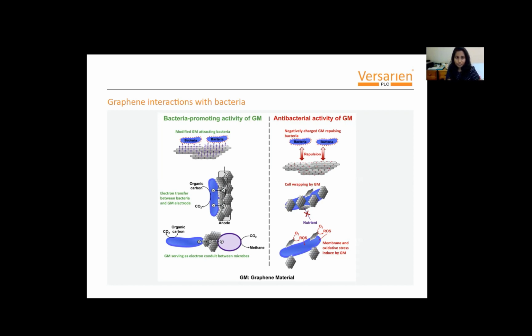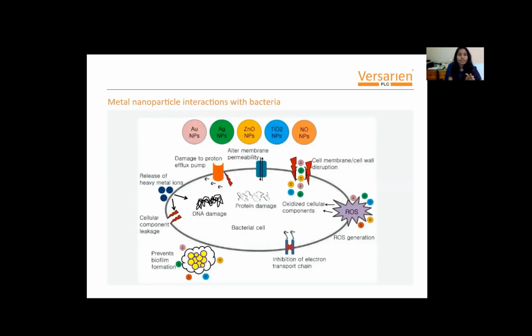Surprisingly and interestingly, graphene materials can promote bacterial activity as well. This all depends on the physical, chemical, electrical, and structural properties of the graphene material that you use. For example, if the surface of the graphene material is positively charged, the negatively charged bacteria are attracted to the surface and get adhered. Then the graphene material can act as an electron donor or electron acceptor and promote the metabolic pathways of bacteria. This is going to promote biofilm formation. So this is proof that we can't use any graphene material and expect to kill any microbial species.